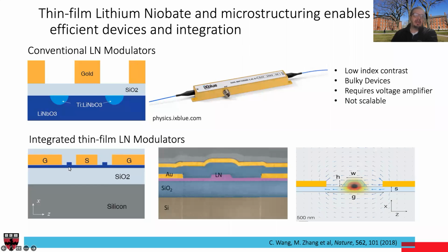Then what one can do is use reactive ion etching techniques and nanostructuring to realize waveguides. Here, as shown in this scanning electron microscopy image, waveguides are realized by partially etching about a 600 nanometer thick layer of lithium niobate, and then cladding it again with oxide on top, and before that placing gold electrodes on either side of this waveguide. Separation between these electrodes in this picture is on the order of 5 to 7 microns. So that just gives you an idea of scale.